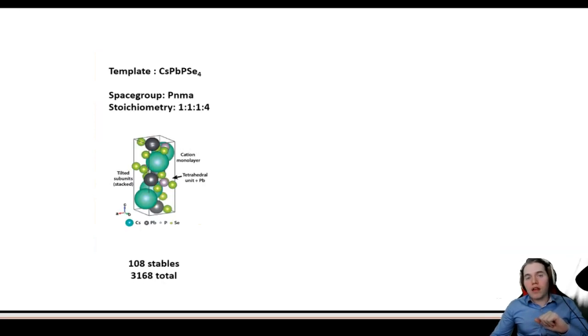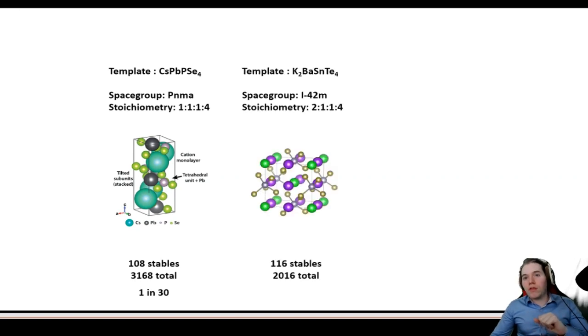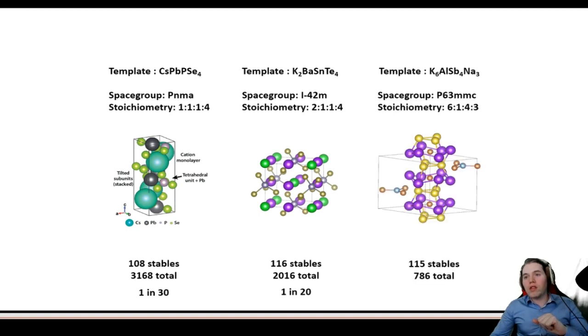So we get again our materials here. And if we do these calculations, which are quite a lot of calculations, about 20 per material, so like 60,000 calculations, we see that we get about 108 stable materials, which is much more than the around 6, I think, there were originally, which is about 1 in 30 here. For this material, we found another 100, which is about 1 in 20. And for this material, we found another 100, which was here 1 in 8.